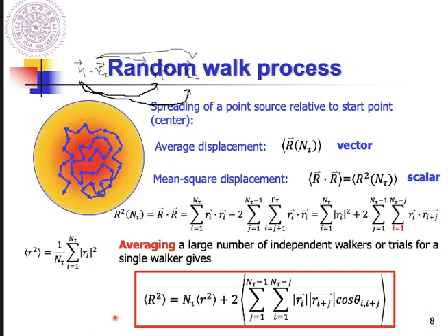Okay, so let's answer whether this mean square displacement can be a good indicator to describe the diffusion phenomena and also link with the atomic jumping process. Based on our derivation, we find that the mean square displacement is related to n tau, the total jump number. So when diffusion time increases, the jump number increases in the meantime. So yes, it can well describe the diffusion phenomena on the macro scale, right?